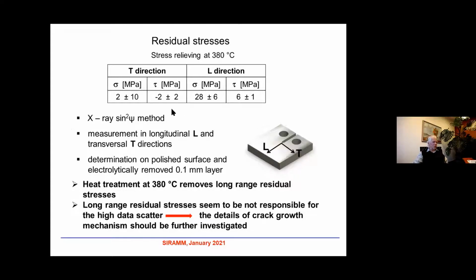We used the X-ray sin squared psi method, and we determined the stresses on a surface which was electrolytically polished and then electrolytically removed nearly 0.1 millimeter, because if you only polish the surface, you can produce residual stresses. So we were surprised that after this heating, stress relieving, the residual stresses were really extremely low. We found only 2 megapascal in the T direction, and shear stress minus 2 megapascal, which is nothing. And in the longitudinal direction, only 28 plus or minus 6, it is really nothing.